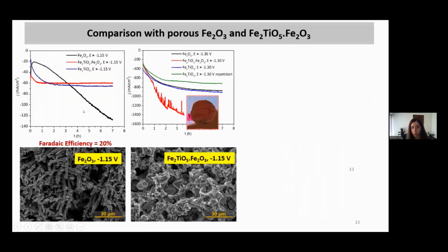So here we can compare with the reduction of hematite and with the composites. The first thing that you can see is the difference between the hematite curve and the others. It starts quite slowly. We have lower current densities, but it increases sharply after 7 hours. And in the hematite case, we observe only dendritic metallic iron near the current collector. This pellet was not completely converted to metallic iron. We still have some traces of magnetite and hematite far away from the current collector.